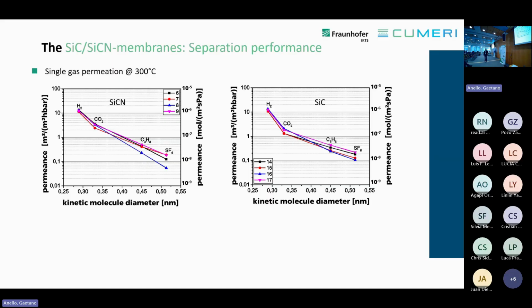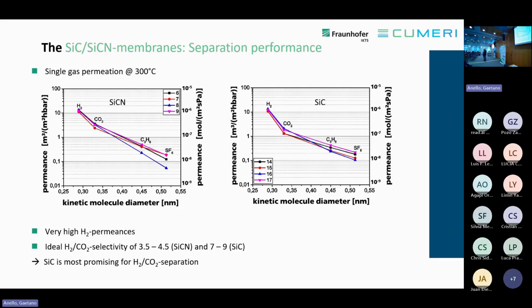For both cases, we got lower permeances for the bigger gases. We got a certain ideal selectivity for hydrogen over CO2 in the range of 3.5 to 4.5 for the silicon carbide nitride, which is above Knudsen, and quite nice, in the range between 7 and 9, for silicon carbide. So silicon carbide seems to be the most promising membrane for hydrogen CO2 separation.